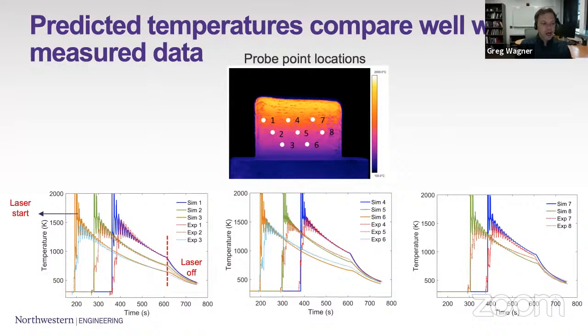It starts to cool. One other thing you can note is that the experiments are not able to capture the initial heating of each point very well. So the region through the actual melting temperature, which is about 1400 or 1500 degrees K in this case, the experiments are not getting data there. And in part, it's because the emissivity of this material is changing as it changes phase, and so it's hard to get reliable data, at least in these experiments that were done here, from the melt pool or from that melt bead itself. So in a way, the simulation at least predicts that we get above the melting temperature, which the experimental data doesn't show.